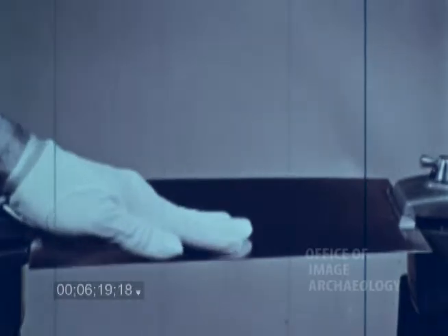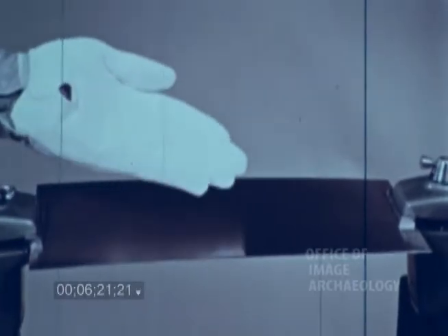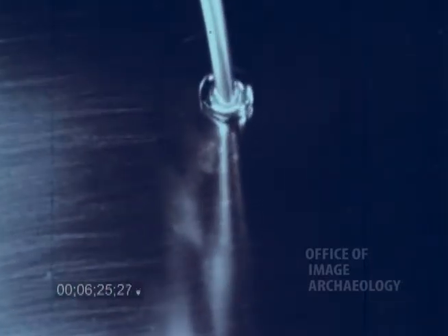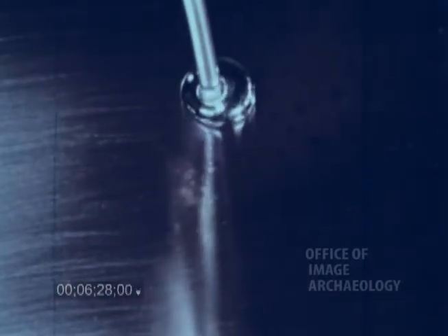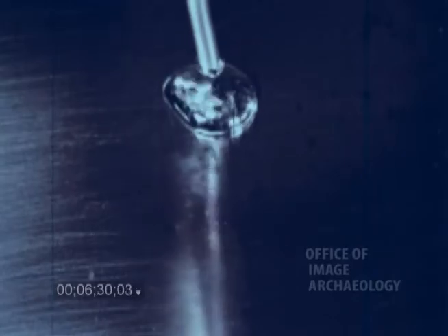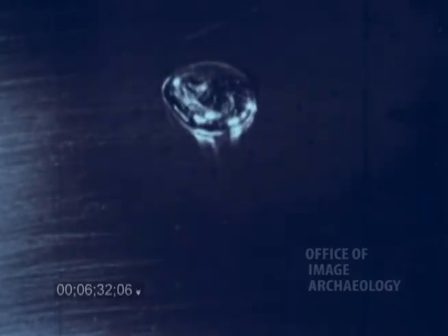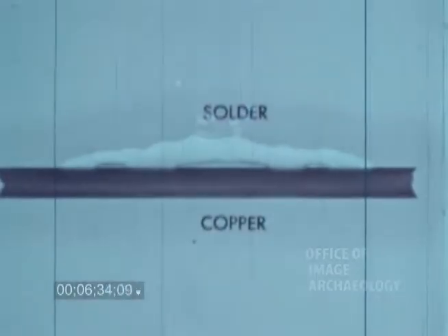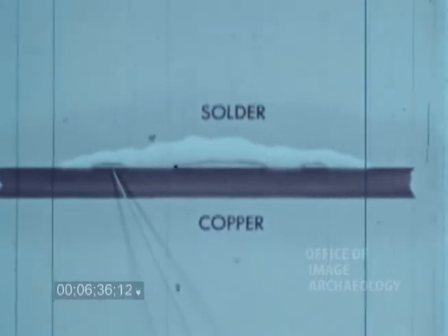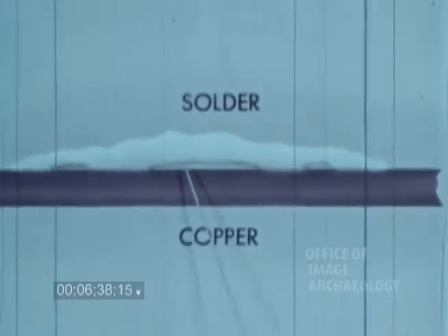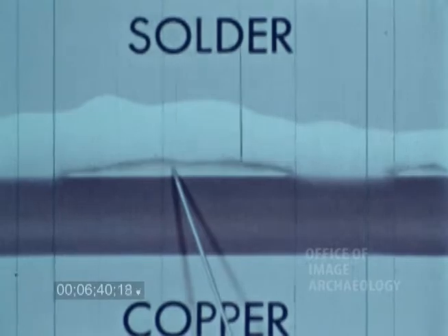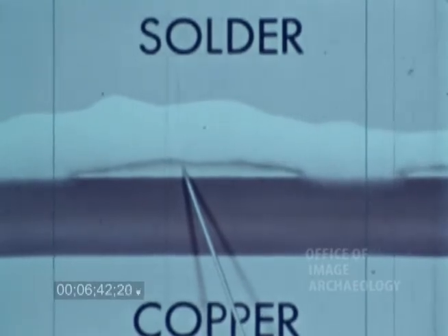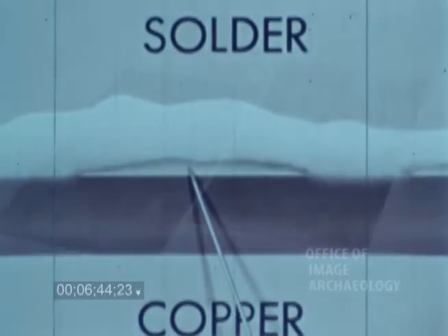To obtain good wetting action is not always that simple. On this thoroughly clean sheet of copper, you will notice a marked difference in the reaction of the solder. It seems to ball up and not flow smoothly as it should. A cross-section would show large areas where the two metals have not blended together. The mixing of the molecules, the wetting action, has not taken place properly.